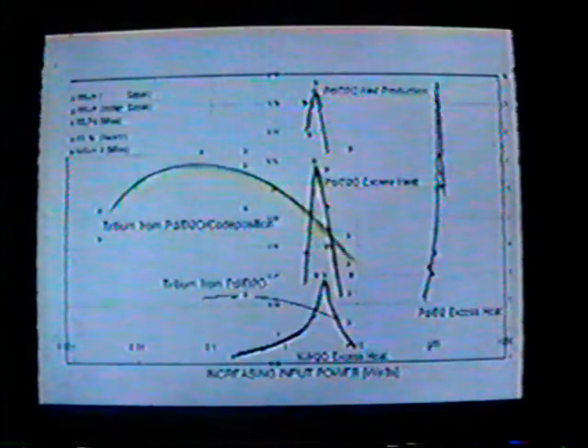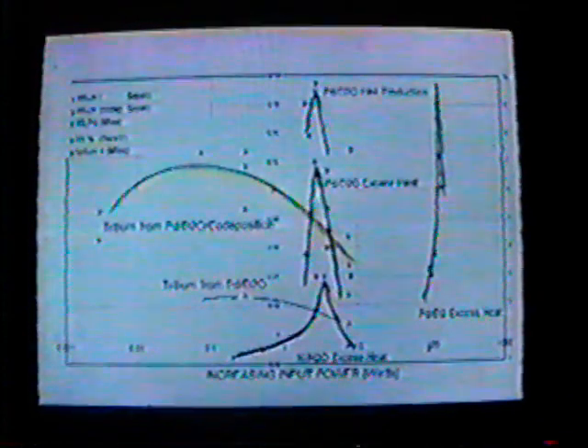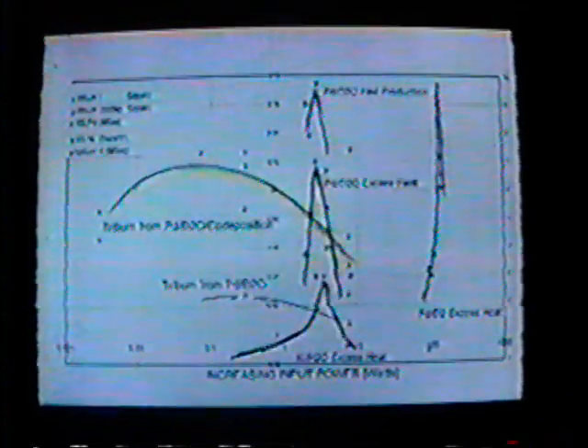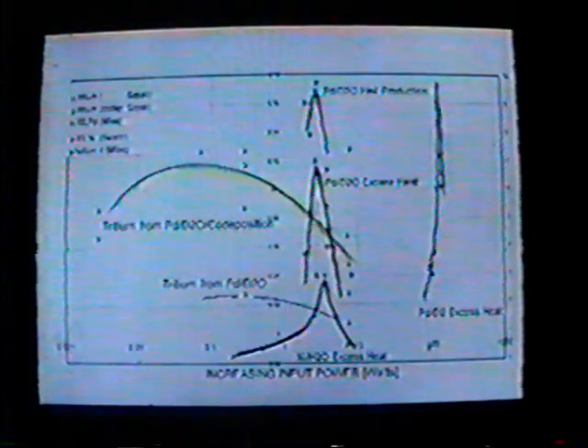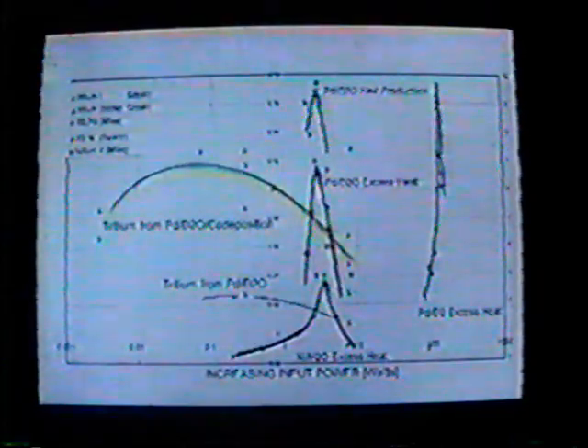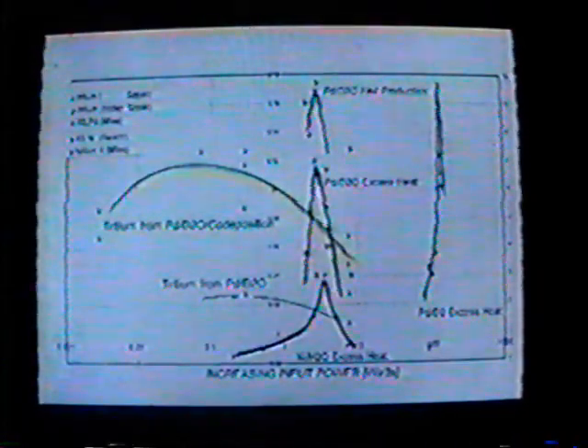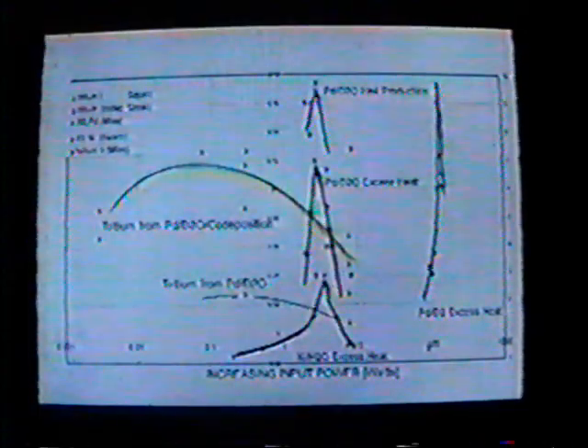They're important because the origin of the heat, that is, at which electrode it occurs, is correlated with the driving of the system with respect to the peak. In addition, the peak indicates a possible role of breakpoints in the power delivery curve. Knowledge of the optimal operating point and the manifold can improve reproducibility and efficacy of cold fusion systems.